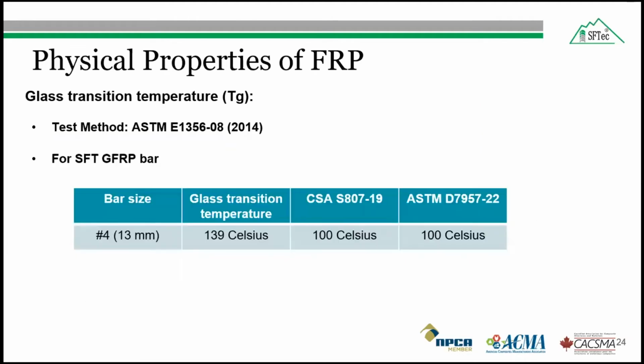So for SFTec glass fiber reinforced polymer bar number 4, the average measured glass transition temperature was 139 degrees Celsius, which was greater than the requirement in CSA S807 and ASTM D7957.